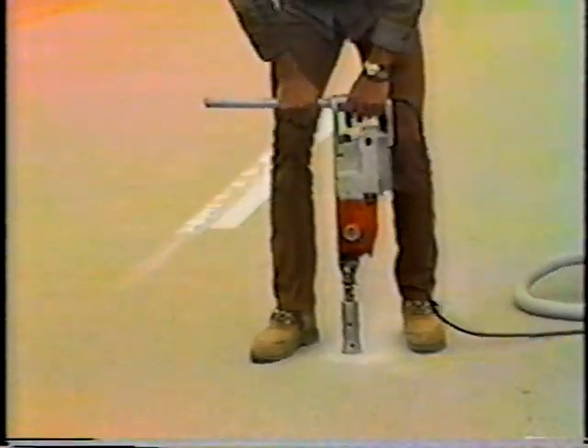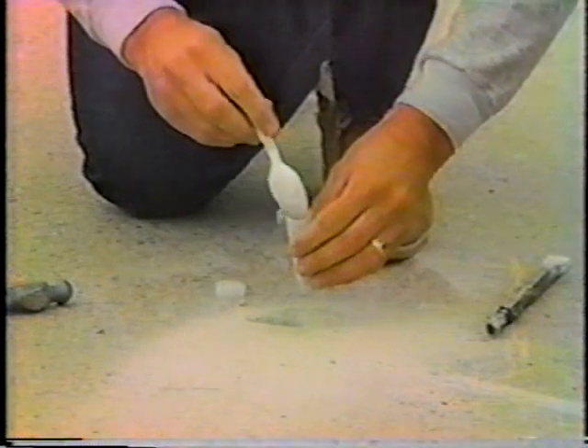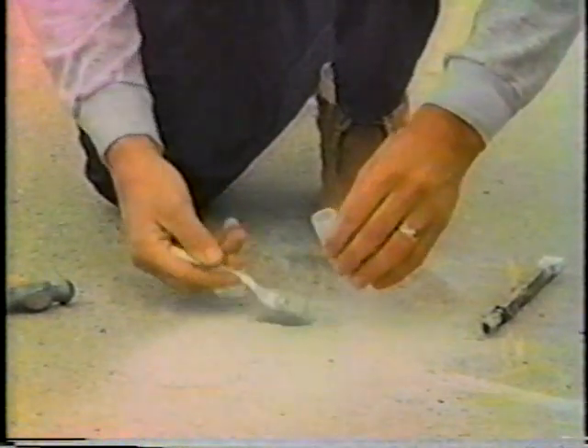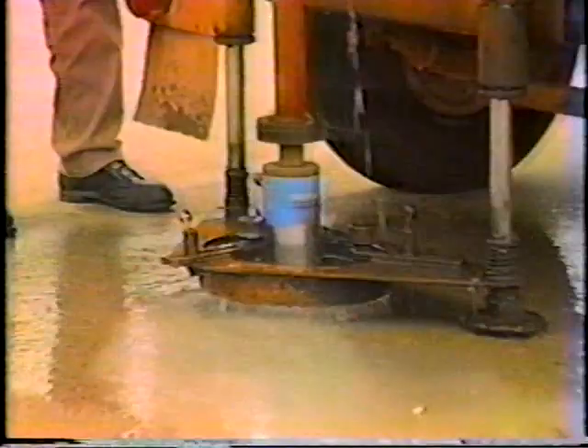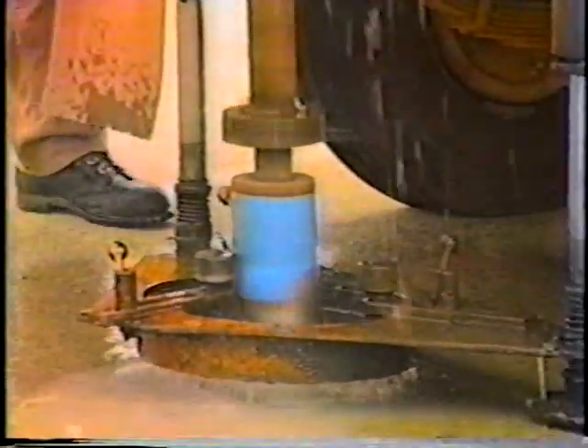In the study shown here, a bridge deck span is marked into squares to facilitate recording the condition of the deck and the logging in of the specimens taken. Many different types of data were recorded. Dry drilled specimens were taken for determination of the degree of chloride contamination. Each type of crack was recorded on the log map. And finally, core specimens were taken so that the absorption and permeability and the parameters of the air void system could be determined in the laboratory.